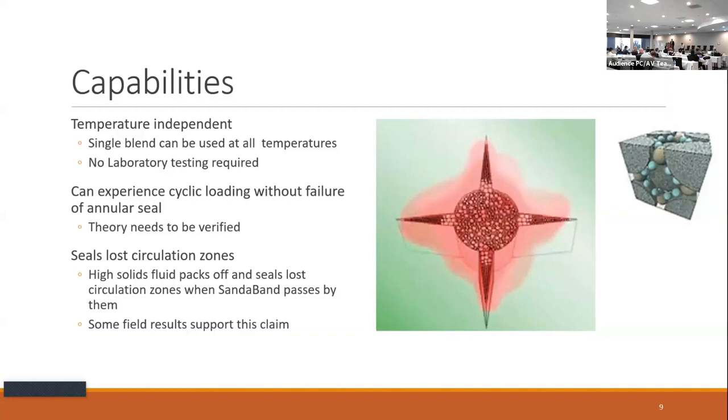They put it in a well. It was originally designed for abandonment. They put it in a well to temporarily abandon it for, I believe, a year and a half. They came back after a year and a half. Instead of having to drill it out, they just washed through it, and it worked just fine. Another unique feature of this particular material is it seals loss circulation. So while it is very heavy,